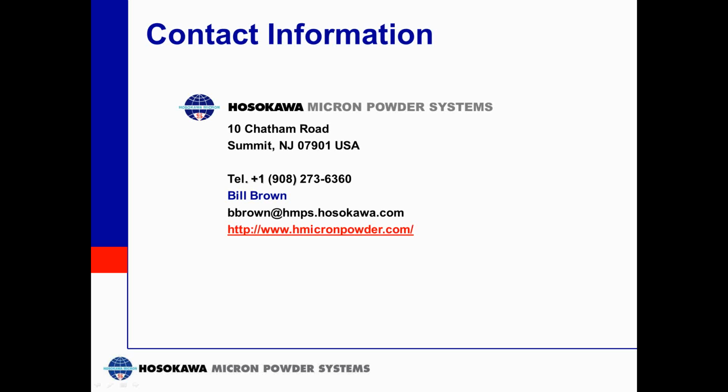Okay. How much material is lost or separated in a separator system? I guess you're talking about the air classifier, the Micron separator. The Micron separator can be used to make different grades as well, and by grades I mean different particle sizes. If you want to achieve, say, less than 5 microns, we may be looking at a fines yield of, say, 95 to 98%. There are a lot of clients who can accept that range. There may be cases where you want near zero or zero grit. In cases like that, we may shoot for a lower fines yield of maybe 50 to 80% to achieve that really clean contaminant-free product, but then take that coarse fraction and grind or grit reduce it with an ACM or ACM2.